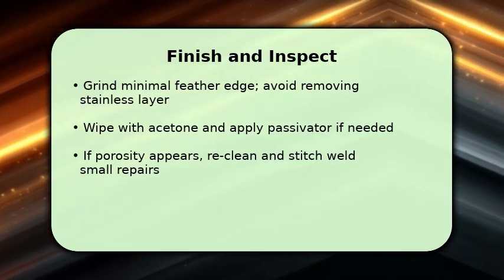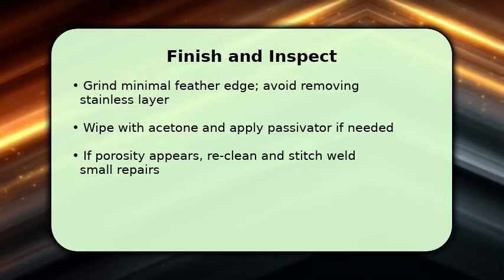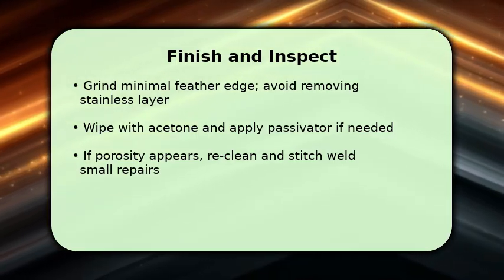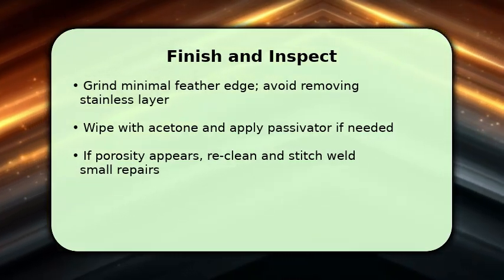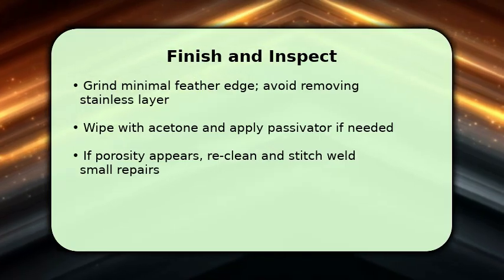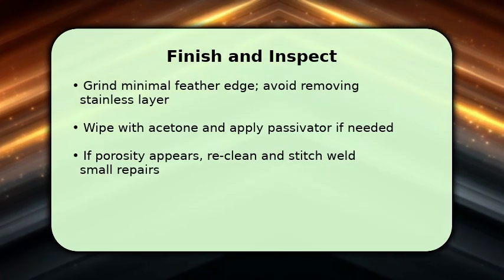If you see porosity or pinholes, stop, re-clean the area thoroughly, and re-weld small stitch repairs. Key troubleshooting. If you get porosity, check gas flow and contamination sources first and re-tack.